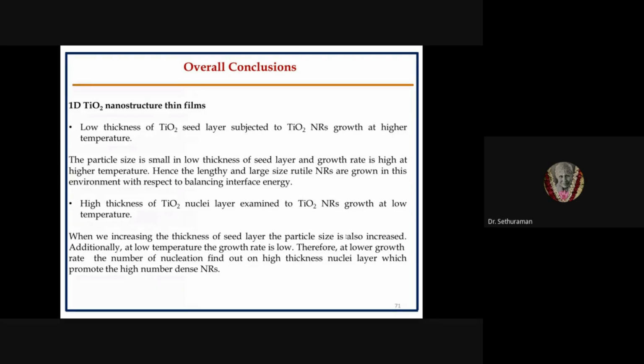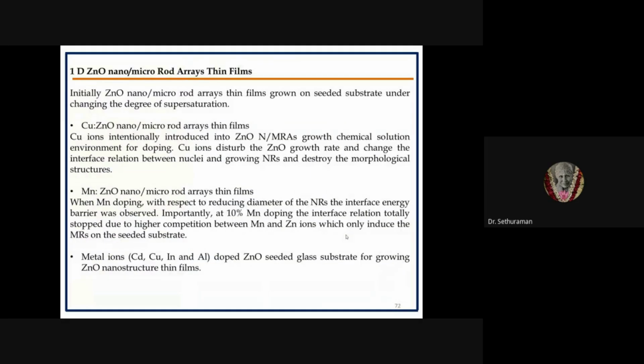In the second case, when we increase the thickness of the seed layer, the particle size also increases. Additionally, at low temperature, the growth rate is low. So at a low growth rate, a higher number of nucleation sites is found on the higher thickness seed layer, which promotes higher number density nanorod growth on the surface of the seed layer. Next, copper doped zinc oxide nano and micro-rod arrays.